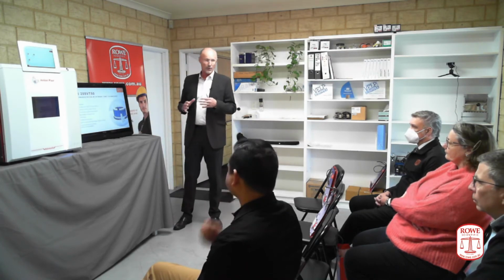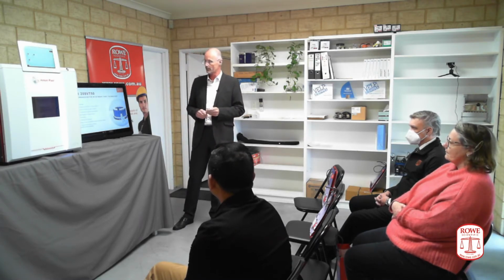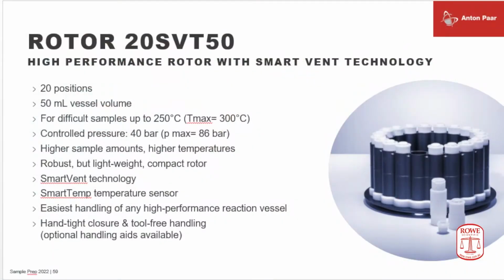If it comes to more difficult samples, like said before, maybe these high pressure systems would not be high enough, and we must go to even higher, superior pressure ranges. Again, we do this in 50 milliliter vessels that can be taken to 250 degrees at 40 bar controlled venting pressure. So this is another range of performance that we are opening up with this type of rotor. At this time, I would like to say a few things about sensor technology.